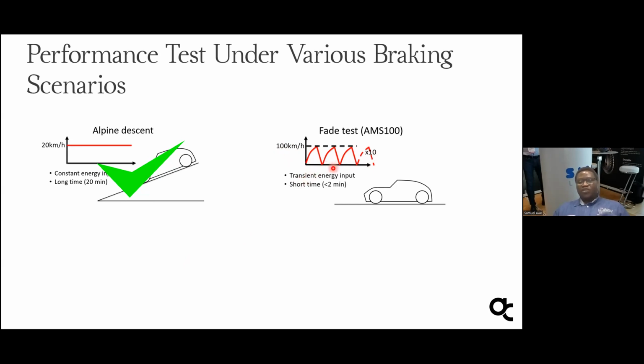So as you do this kind of series of tests, what happens? A lot of energy is built up. A lot of heat is built up on the brake disc and the surface. So this could create a lot of issues. There we can evaluate if there is a thermal crack, because you apply the brake and you continue. So there will be a temperature gradient within the disc, which could lead to thermal crack. You could also have fatigue crack. So all this is evaluated from the disc, and this also must be passed.